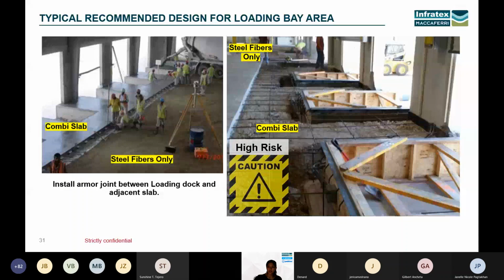So this one is a sample of a typical recommended design for a loading bay area. For loading docks, we recommend using combination slabs using rebars plus steel fibers. Why? Because this is a high-risk area, one of the busiest areas in a warehouse, where cracks are likely to happen. This design is actually what we did with our ongoing project in Southern Star in FIT Santo Tomas, Batangas for their loading docks.